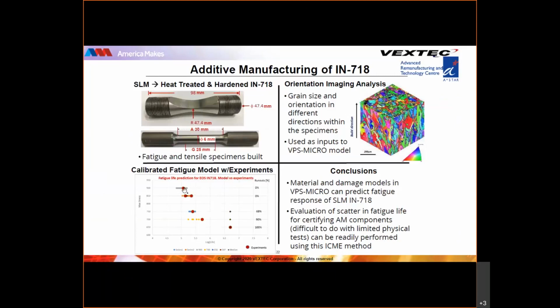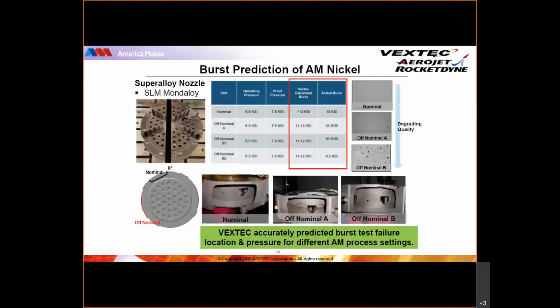And not only in matters of fatigue, we've successfully modeled other mechanisms in the failure spectrum, such as burst failure or overload fracture. Here with Aerojet Rocketdyne, we predicted the burst failure location and pressure magnitude for various AM process settings in Mondaloy. These settings produce different levels of quality in the material, vis-a-vis how many pores and voids were present and their respective sizes, depending on the speed and feed of that AM process.